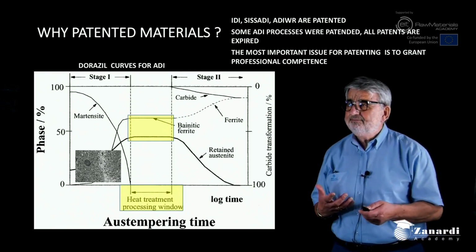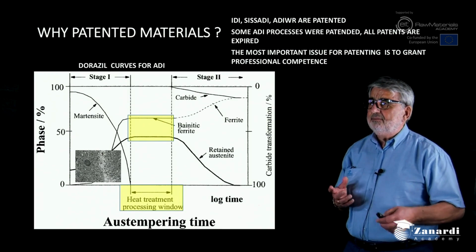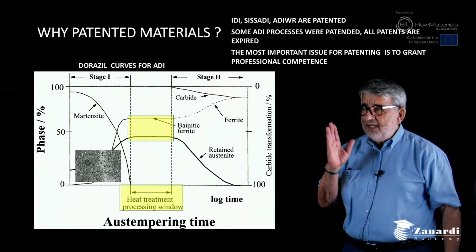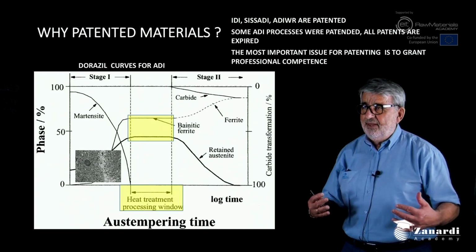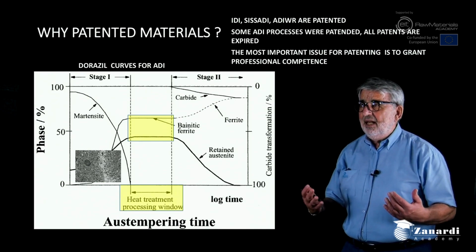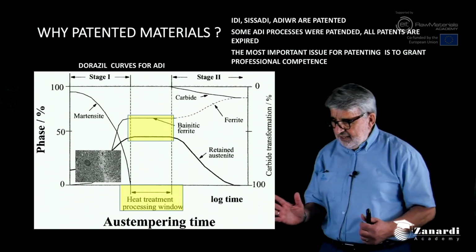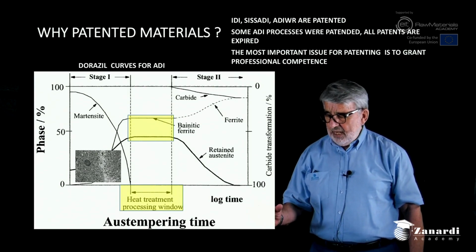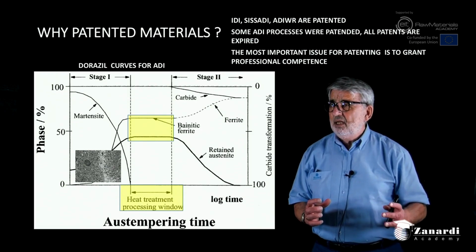And we see why. When we change from the austenitizing temperature to the salt bath temperature, and we start the ausferritic reaction, we know that the ausferritic reaction starts from the first to freeze, from the nodule, and progresses to the grain boundary, to the last to freeze.